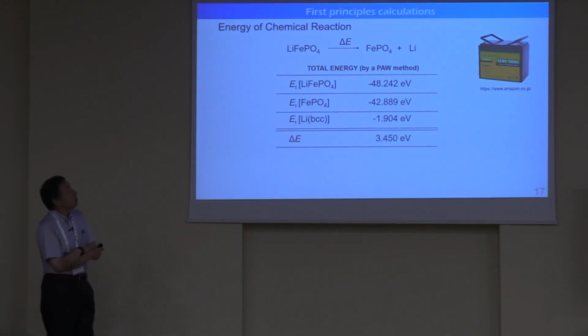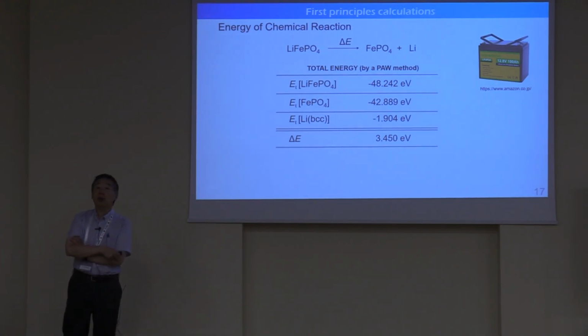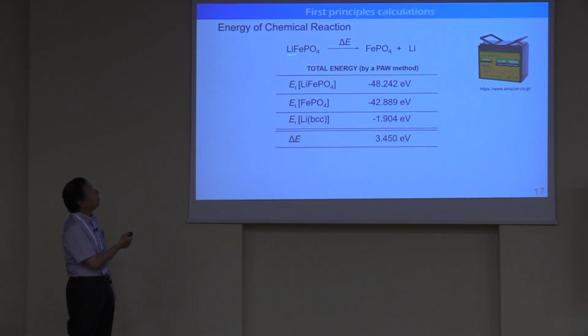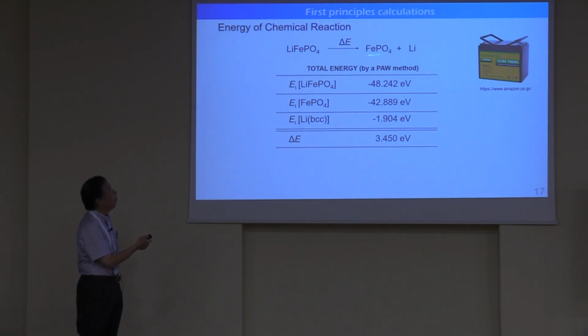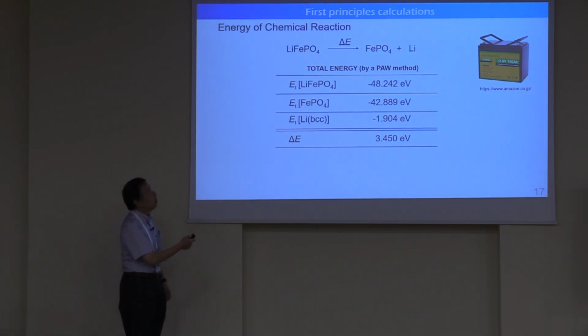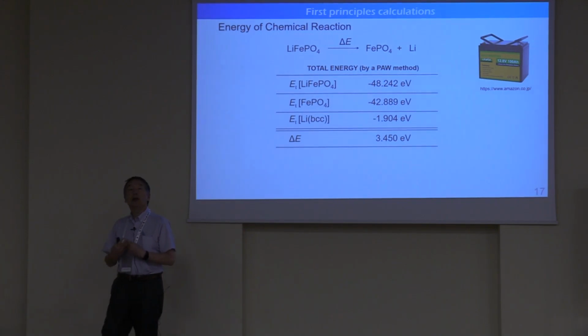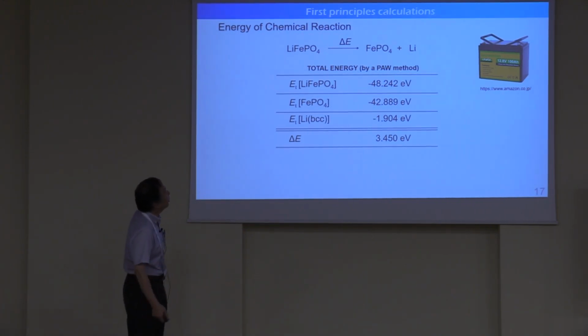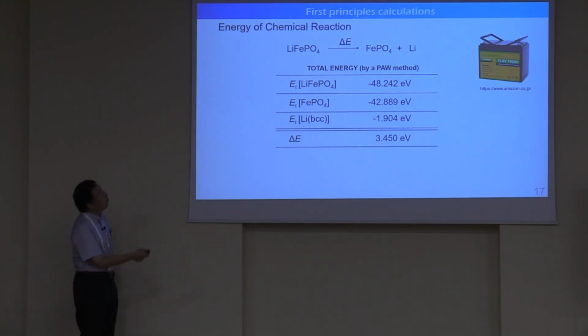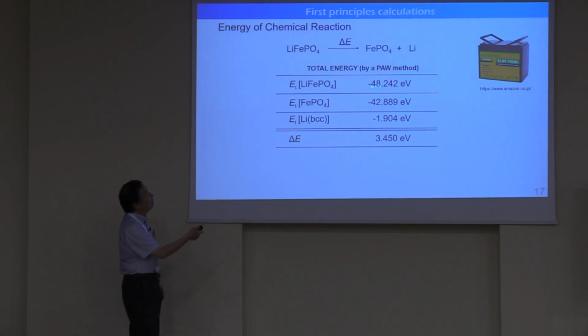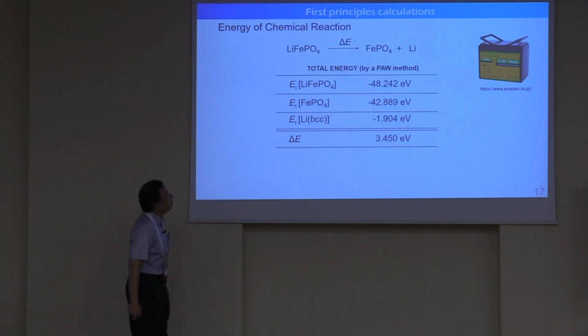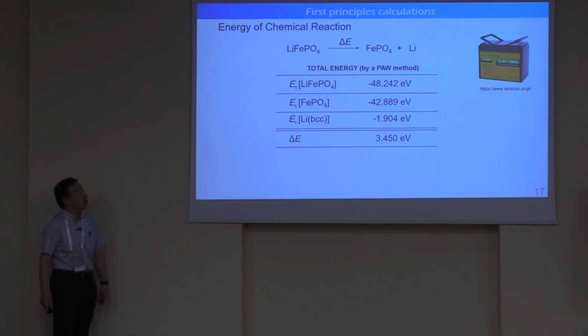One example. This is a lithium battery, which is often used in our daily life. And the battery voltage is obtained by this reaction. Lithium iron phosphate compared to the simple iron phosphate and lithium metal. Sometimes this lithium metal is inserted into carbon materials or some other anode materials. Anyway, to make the story simple, I take this here, lithium. Then performing all these calculations by PAW method, you can obtain these energies, and by subtraction, you can find that the energy difference here is 3.45 electron volt.